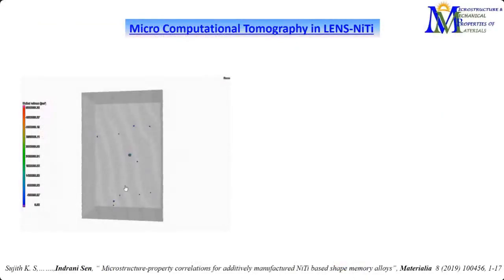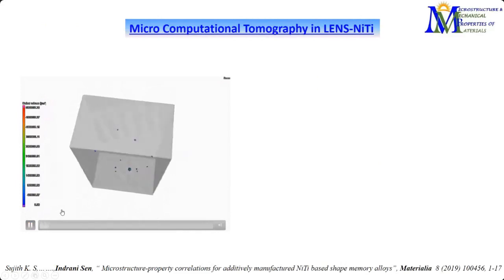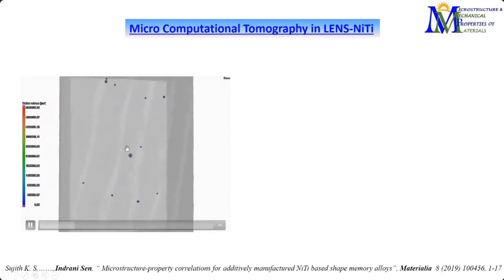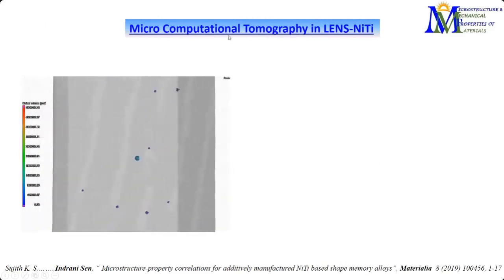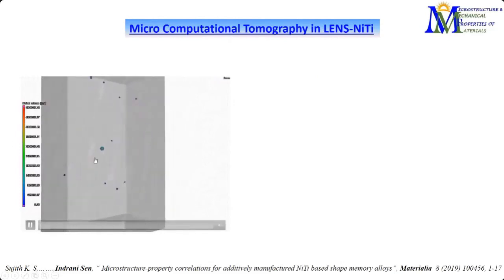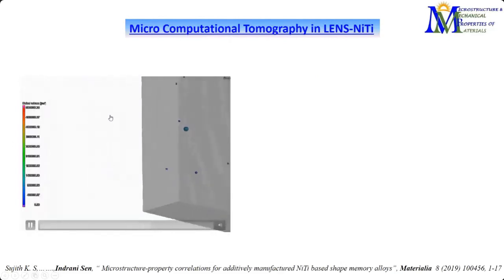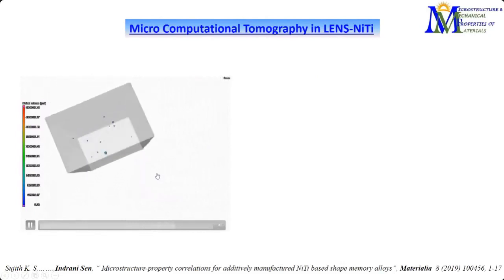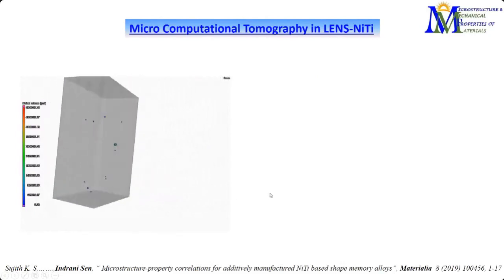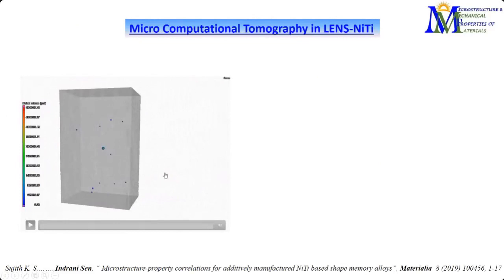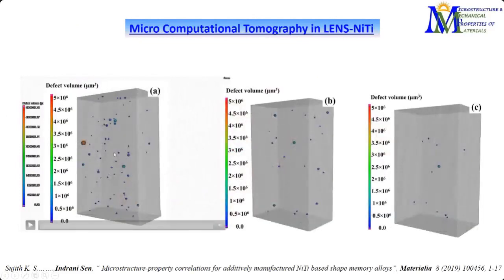Another interesting thing is the porosity. As I said, porosity is something we can control, and this video shows that we analyzed it through micro computational tomography to see how porosity developed throughout the component. This is for one particular alloy system made with the highest energy density, but comparing all three, the one prepared with the lowest energy density has a lot more porosities.